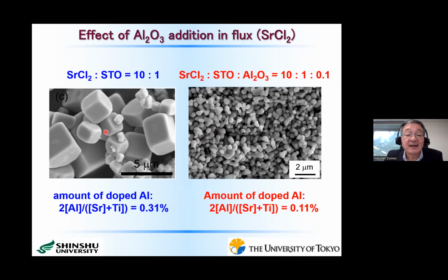Okay, on the left-hand side SEM image, I show the sample prepared by only using the strontium chloride as a flux. And this is a 5 micrometer scale bar, so the particle size is considerably large and not really homogeneous. And in this case, the amount of doped alumina was about 0.3 atomic percent. However, if we add 1% alumina against this strontium chloride, then, as you see here, the particle size becomes much smaller and almost homogeneous. And the amount of doped alumina was about 0.1%.